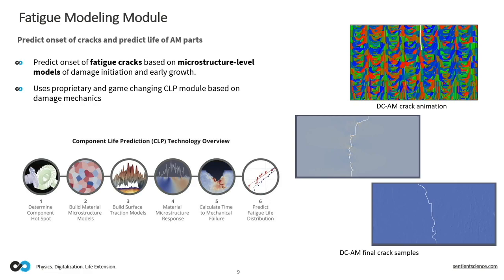What is missing in that is that when you assume that initial crack, you are overlooking your crack initiation stage. And most of our customers are in aerospace, and in aerospace, crack initiation stage is all they care about. So you cannot do that one with fracture mechanic, right? This one can predict the crack initiation stage, which, when you're talking about high cycle fatigue, could be all the way up to 90% of the entire life of the part. And that's the value right there.